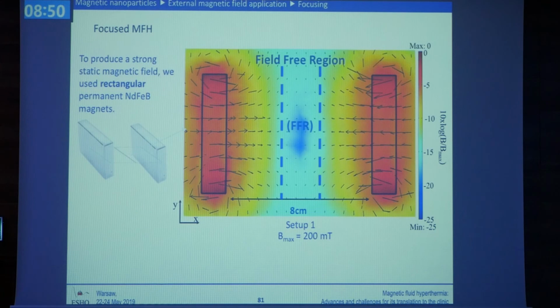The other setup that we're trying in our lab is focused hyperthermia. So instead of having only an external alternating magnetic field, we also have a static magnetic field. A static magnetic field makes the nanoparticles, like compasses, direct themselves and stabilize on this external magnetic field, and they don't rotate with the alternating external magnetic field. But they rotate only where your static field is zero. That's what we call the field-free zone.